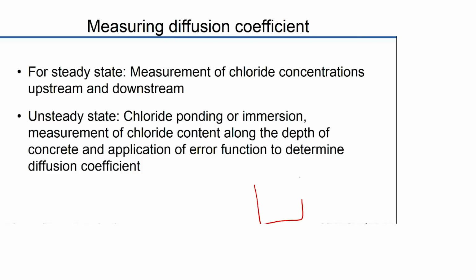So here you have a tub filled with chloride and you put your cylindrical concrete specimen within this tub. And what happens is the chlorides will tend to diffuse unidirectionally from the top of the concrete specimen. So you need to cover the perimeter using something impervious like an epoxy coating, okay, so that the chlorides do not penetrate through the coating. They only penetrate unidirectionally.